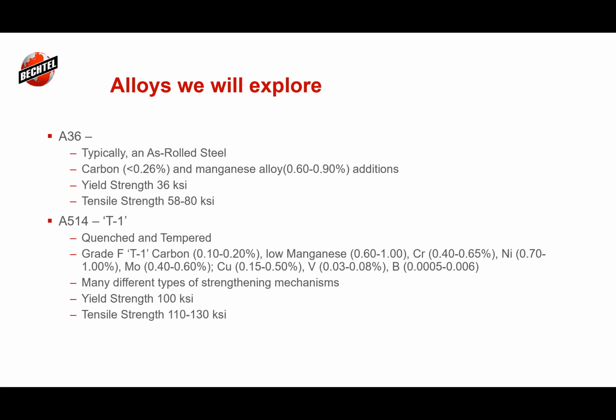far as alloying elements. So the 514, I have a tendency to call some of these steels the kitchen sink steels, and I call them the kitchen sink because it's sort of like everything that was in the kitchen sink fell into the melter to be able to make these steels. There's a lot of activity happening, as well as the heat treatment that is going through the quench and tempering. And of course, the yield strength is over 100 KSI, and then the tensile strength is 110 to 130. And all of the 514 and the 517 grades sort of fit within that range.